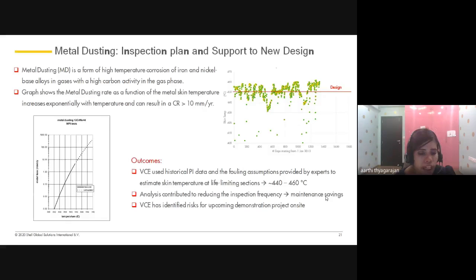And we had done some experimental studies for some specific choice of materials used in these specialized heat exchangers, and what you see in the graph is nothing but the metal dusting rate, or corrosion rate, as a function of metal skin temperature. Again, here it is the skin temperature that is the major cause of the degradation of the metal. So what we came to know is that at a temperature of 450 degrees Celsius, the corrosion rate was consistently about 0.2 millimeter per year, and a temperature limit was hence enforced to mitigate corrosion.